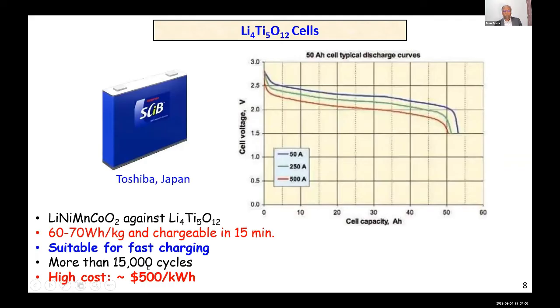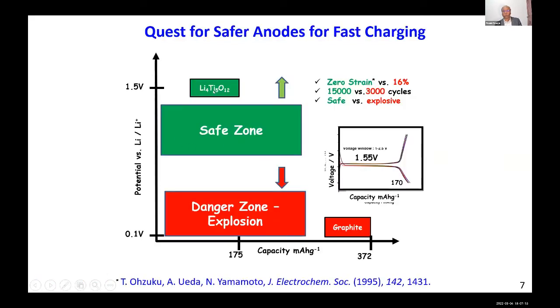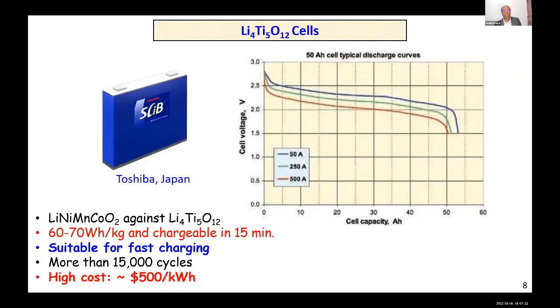And then you may ask, what is the problem? Why can't we go ahead with that? The problem is the following. The problem is because the lithium titanate is operating at 1.5 volt and the cathode is operating somewhere about 4 volt. So the typical voltage is in the range 2 to 2.4 volt, and hence the energy density is far less as compared to LFP graphite.